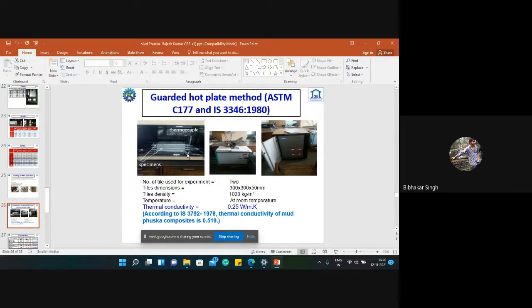After 28 days, we conducted the guarded hot plate method test for our tiles. The thermal conductivity result of our tiles is 0.25 watts per meter Kelvin, which is according to IS 3792. The thermal conductivity of mud phuska composites is 0.519. So in our case, this is much below what is mentioned in the IS code. So this is the finding of our research work.